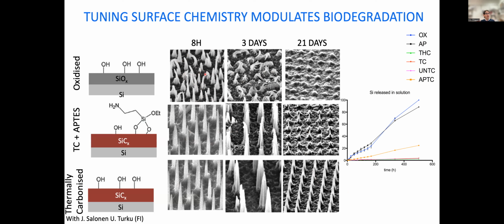We can either have materials that are very quickly degrading, so we can use them to deliver very quickly, and then they just dissolve and disappear in the interaction with the cell, or materials that have an intermediate degradation within a few weeks, or materials that are fundamentally long-term degrading or almost stable, that can be implantables and can last for months in the body.